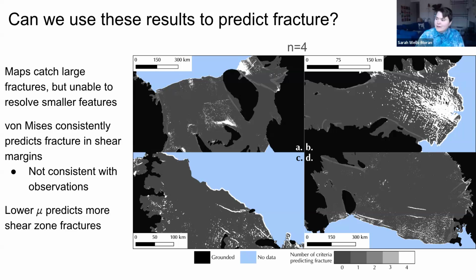And kind of unclear as to why that might be. This region on Amery is quite interesting because these linear features here are all fractures that are observable on optical imagery. They also show up in the strain rate fields. We just didn't include them because of their proximity to the shear margin, but this map does accurately capture all of those. And then this is the fracture that formed the A68 iceberg and very clearly picks up on that.